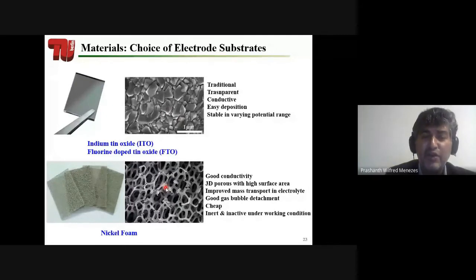But very recently, a new electrode substrate such as nickel foam has come into play because it also has very good conductivity. It has a very porous surface and improved mass transport. That means when you produce your hydrogen and oxygen, you don't want to have them at the same place. So you want to move them out of the system. Since it has three-dimensional pores, it just transports the oxygen and hydrogen out of the system. It is relatively very cheap. And also, as I said, like FTO, it is inert in the operating conditions of our reaction.